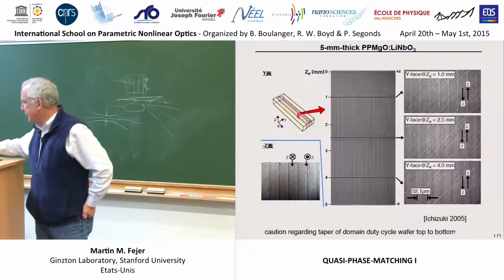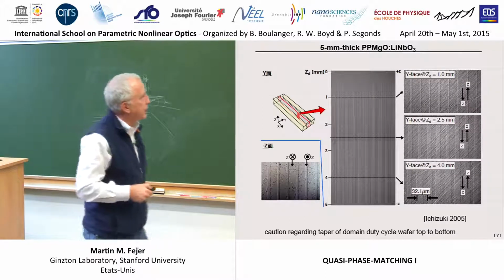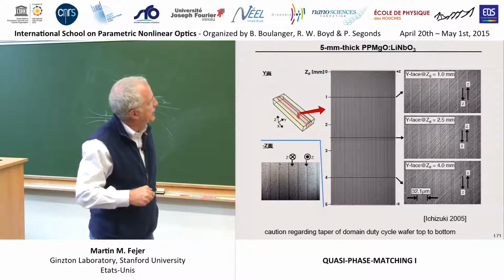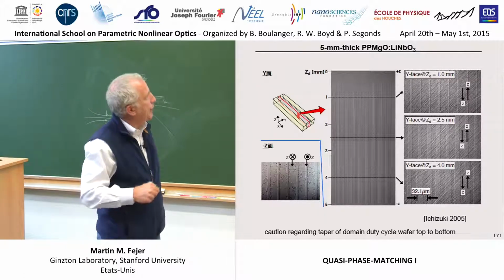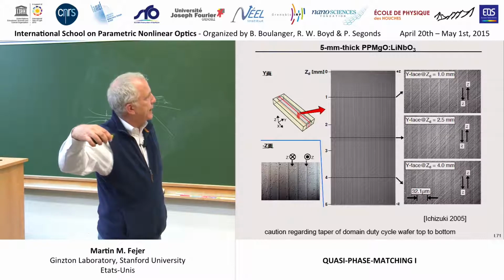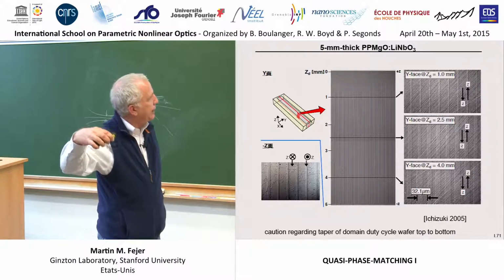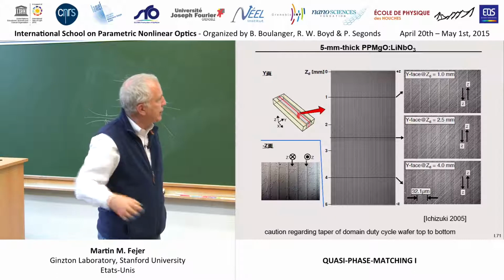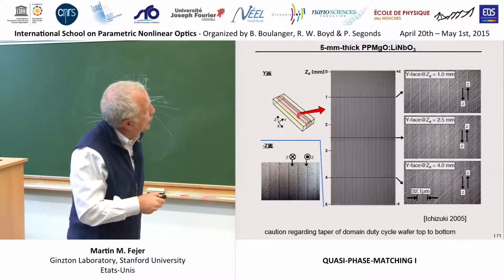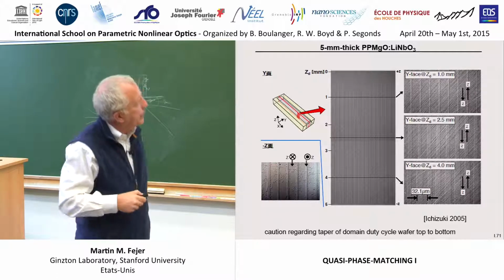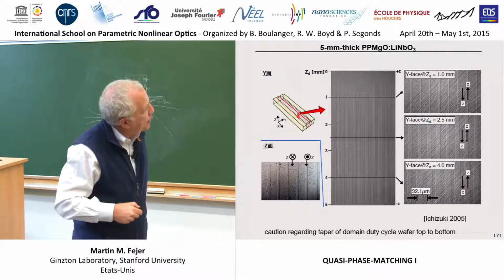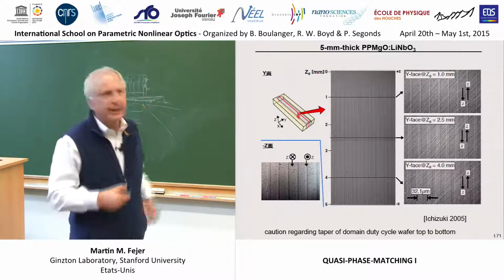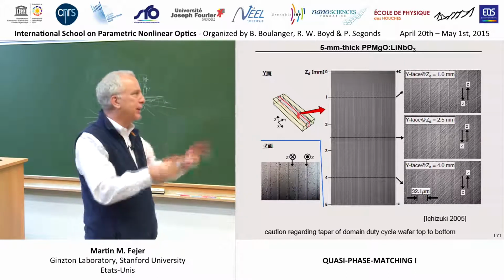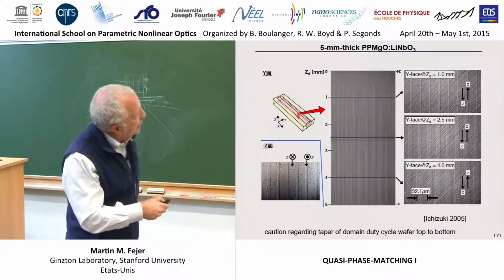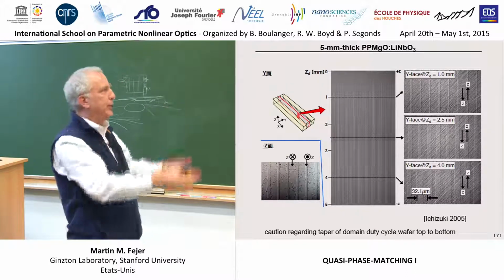Let's not talk about the details of that apparatus. This is a picture from one of his papers. So this is a 5 millimeter thick wafer, and it's looking in at the side of it, so the domains are alternating up and down here. It's not a real high contrast picture, but if you look near the top, the middle, and the bottom, you can see the width of these domains is getting wider and wider, the light-colored domains. Differential etching shows up the plus and the minus domains. The domain width is tapering through the thickness.